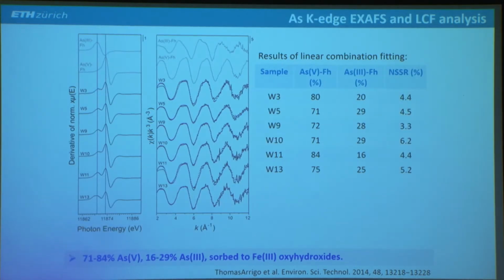If we look at the arsenic EXAFS spectra, this time we only needed 2 reference spectra to describe the unknown samples. These are shown on the top, arsenic-3 and arsenic-5 sorbed ferrihydrite. These are 6 different flock samples. You can see they all look more or less the same, and they can all be very well explained by these 2 references. And the summary of this is that arsenic is mainly adsorbed to iron oxide minerals, and it's 70 to 84% arsenic-5, and 16 to 29% arsenic-3.